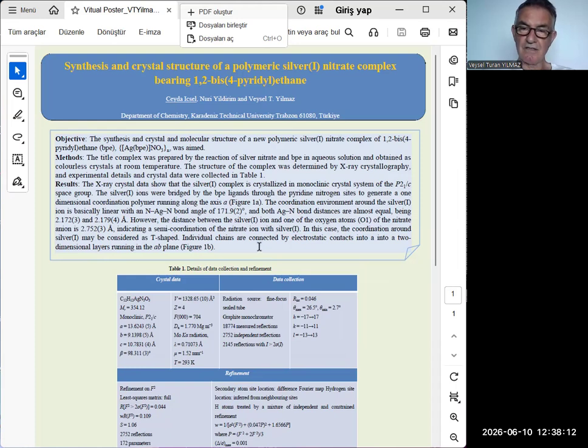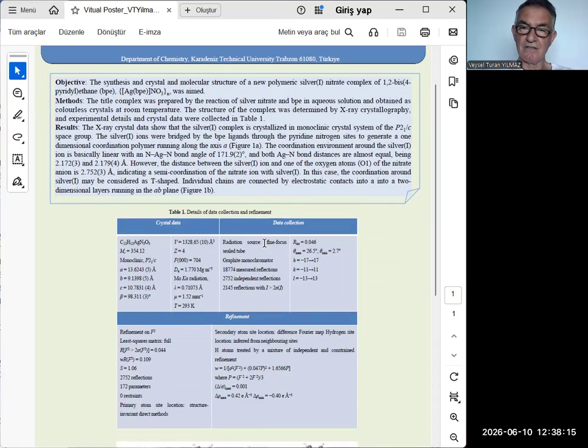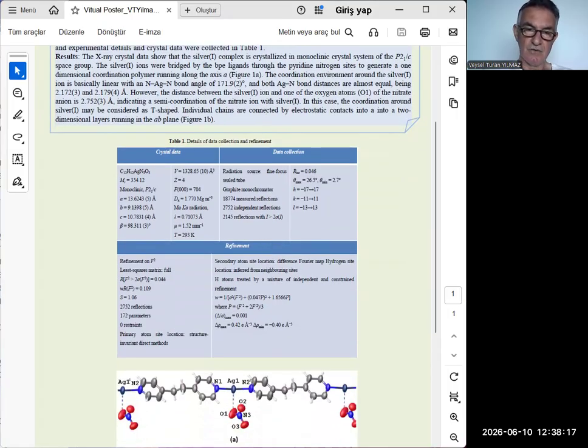If you look at Table 1, you will see details of data collection and structure refinement of this complex. X-ray measurements show that the silver complex crystallized in the monoclinic crystal system. Although the crystal quality is not good, the refinement parameters were fine.